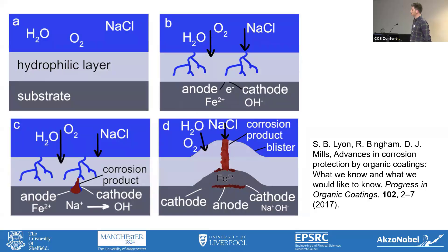When we think about a polymer coating, we often think of a coating that is a very good barrier layer. Some of my colleagues would say water isn't getting near to the substrate. But what we've begun to realize is that water has a permeability — it might be slow depending on whether it's a semi-crystalline polymer or not — and it will get through a layer over time. We're trying to understand the mechanisms by which we get to this sort of 'volcano' end state — the bad thing we don't want to happen in our coatings. They are very important in trying to reduce our environmental impact and protecting infrastructure and other materials which are expensive to replace.